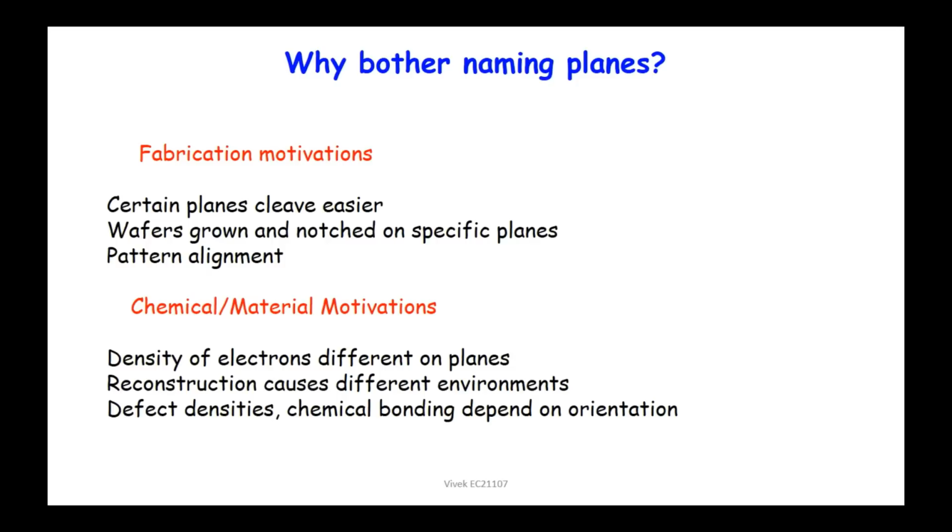It is more reactive. So for example, if you have a silicon substrate with a 100 surface, and you etch it with potassium hydroxide, it will preferentially etch along the 1 1 1 plane. So that will not be exactly perpendicular, right? That will be somewhat slanted, there is some angle, right?